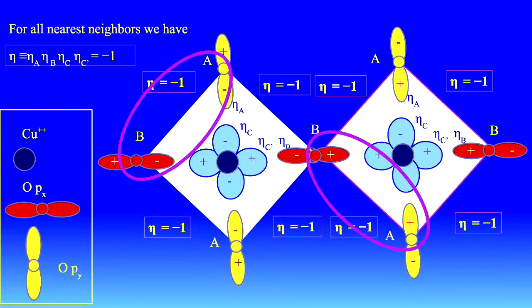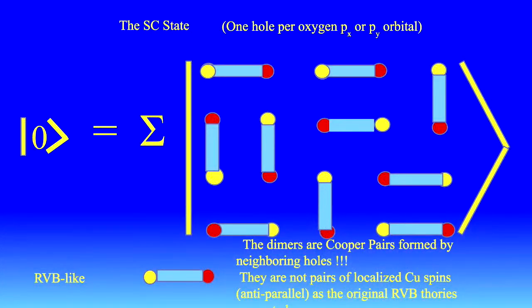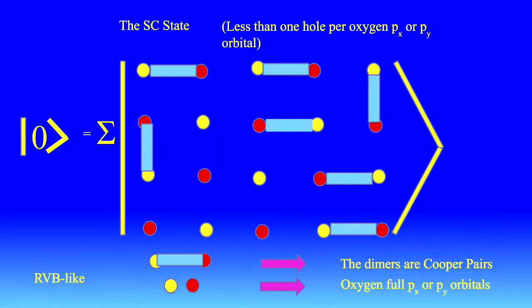So this provides the superconducting interaction. The superconducting ground state is a sum over all combinations of dimers in which we have this, a Cooper pair. So this is similar to the famous RVB state, which was proposed by Anderson a long time ago. But the Anderson proposal, the RVB, was a ground state of the Heisenberg antiferromagnet, and the dimers were pairs of antiparallel spins. Here the dimers are Cooper pairs. So this is a difference. This is our vacuum.